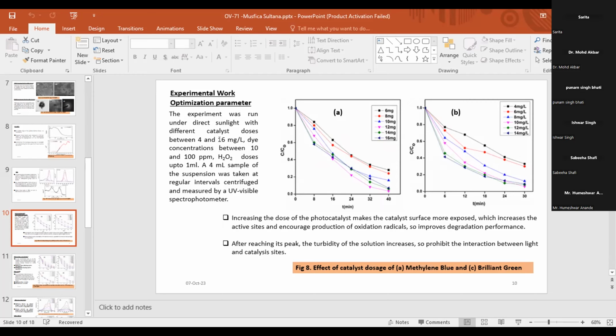From the graph, it is seen that for methylene blue, 12 milligram has given much degraded product, whereas for brilliant green, 10 milligram per liter has shown much degraded products, because increasing the dose of the catalyst makes the catalyst surface more exposed, which increases the active sites and encourages production of oxidation radicals, so it improves photodegradation performance. After reaching its peak, the turbidity of the solution increases, which prohibits the interaction between light and catalyst sites, and because of this, the degradation decreases after a certain point.